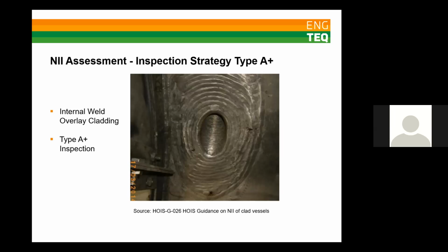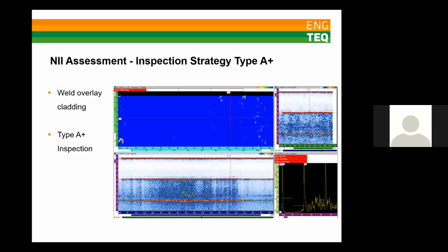This is given the very low amplitude of signals obtained from the more localized forms of stress corrosion cracking. The higher level of signals from a more extensive form of stress corrosion cracking would be more likely to be detectable, but there's currently no published evidence available to support this. So we have to come to the conclusion that it may not be possible to detect fine pitting or stress corrosion cracking in weld overlay cladding. But then these are the morphologies of concern most often in stainless steels. So how can we inspect weld overlay clad vessels if there's no reliable way to detect fine pitting or stress corrosion cracking? We have to look at the interface and the carbon steel substrate itself for signs of damage.